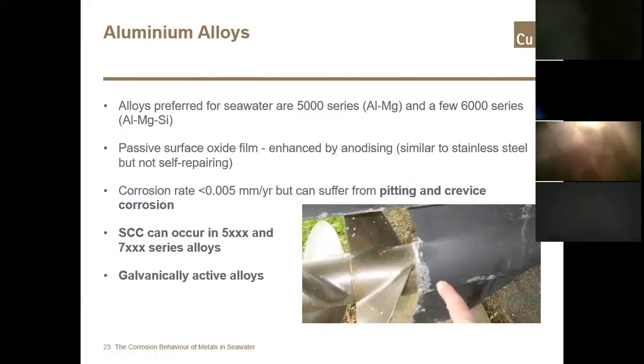The aluminium alloys, generally the 5000 series are preferred for seawater use, with a few of the 6000 series. The 6000 series offers higher strengths to the 5000 series. Now, the aluminium does actually offer a very low corrosion rate of less than 0.005 millimeters per year. But it is a galvanically active alloy, so if you are using it as a main alloy, then you have to ensure that the galvanic protection is in place, so that it doesn't become the sacrificial anode, because the passive film that protects the aluminium is not self-repairing. It can be enhanced by anodizing and coating, but it can cause issues if it does get damaged.